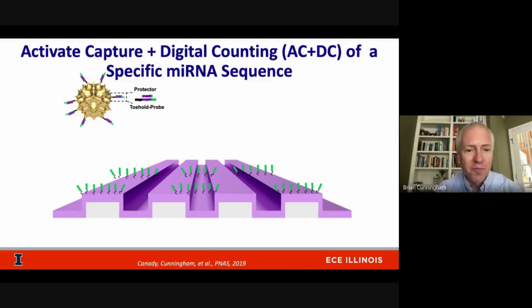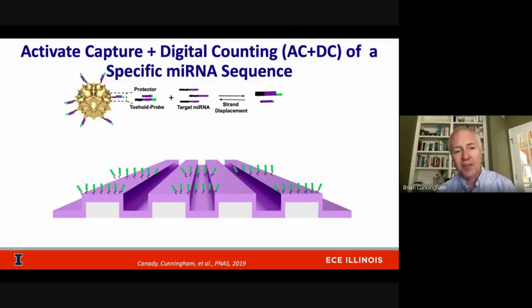So the toehold probe contains a complementary match to the microRNA sequence we want to detect. So our test sample, like the serum from the cancer patient, has a microRNA with a specific sequence that we want to detect. The toehold probe molecule has a complement to that sequence, but that complement sequence is protected by this nucleic acid that's called the protector. Now, what occurs is when the target microRNA reaches the toehold probe, they have an interaction called strand displacement, where base by base, the target microRNA attaches to the toehold probe and forces the protector to go away. So when the protector goes away, now it's kind of floating around free.